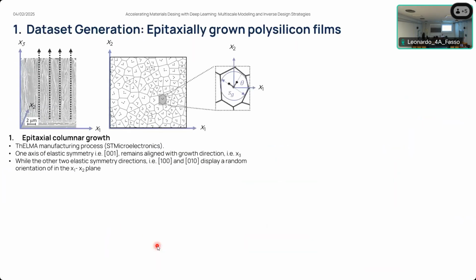So in terms of the first step, dataset generation, here we deal with the epitaxially grown polysilicon thin films. These films are characterized by a columnar growth, where one of the axes of symmetry can be regarded as remaining aligned with the growth direction, which in this case is represented by the third axis of the global reference frame in this diagram, while the other two elastic symmetry directions display a random orientation in the x1, x2 plane.